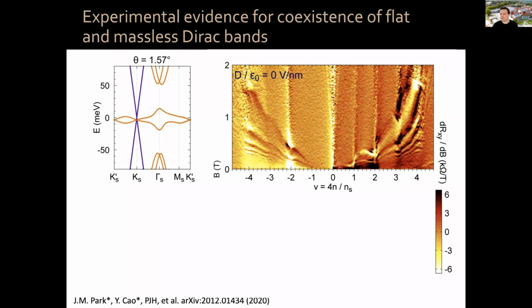And the reason why you see it waving rather than straight lines as you would usually see it is because what you're seeing is the actual chemical potential of the magic angle bilayer-like band measured by the Landau levels of the monolayer-like band, okay? So this is something that we have investigated also in coupled monolayer-bilayer systems, except that now our monolayer band is embedded in the system. So it's quite interesting, and you can read more about this in this paper, okay? And here you can see actually negative compressibility, etc. You take the derivative of this, it looks like the cascade of phase transitions data that I just showed you a moment ago. So this is the monolayer band and the bilayer band.